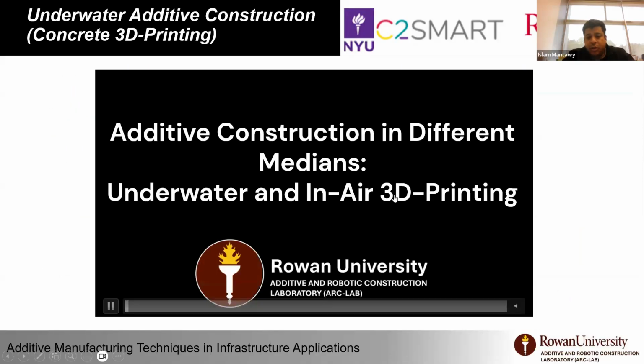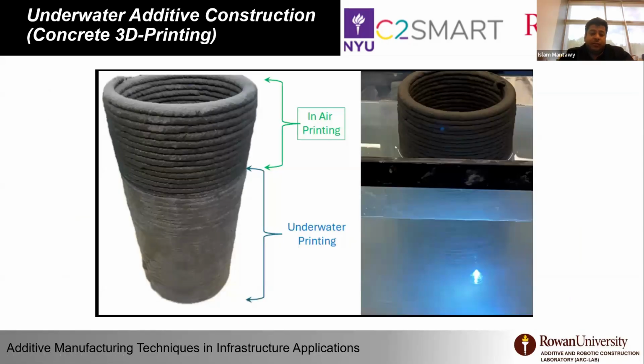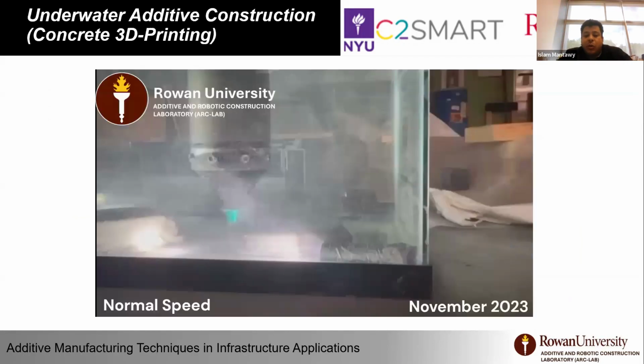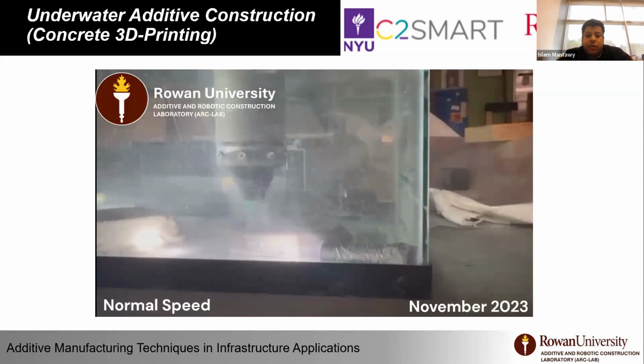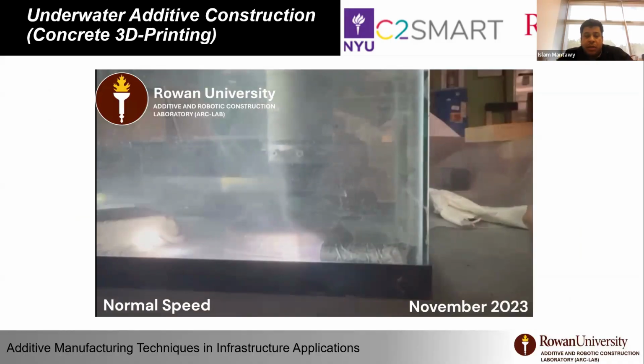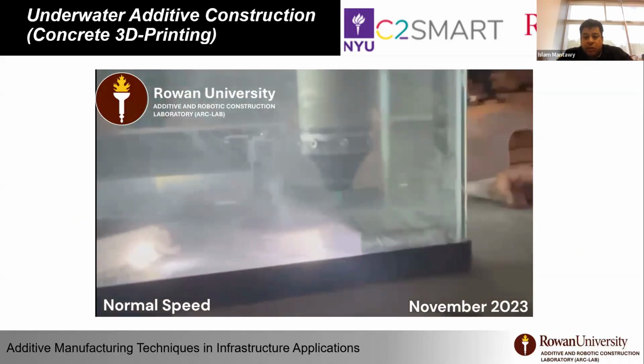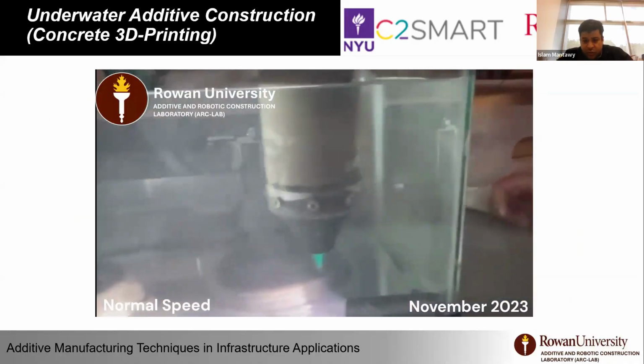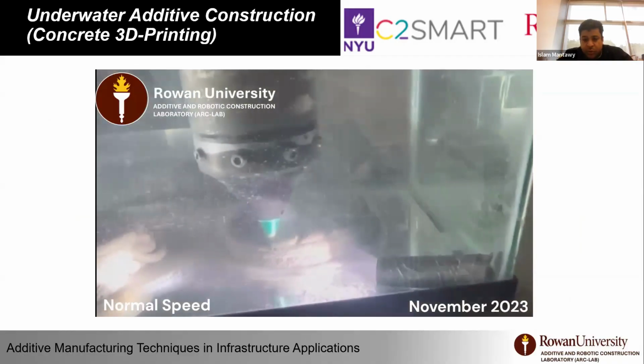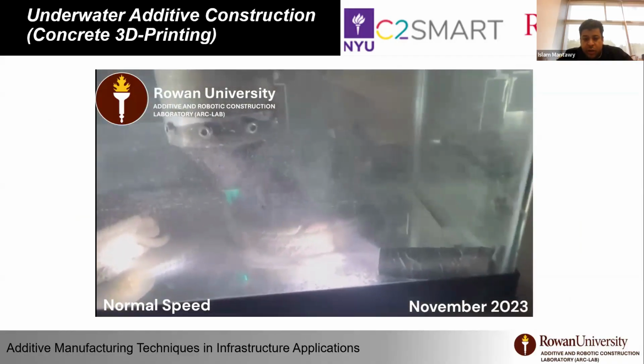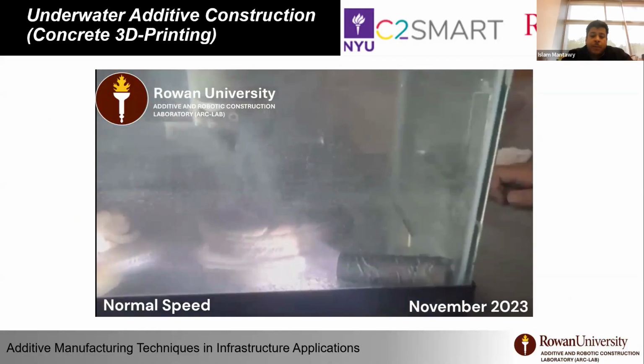In chronological order here from Rowan, we actually think we are one of the first people that printed underwater. That happened in November 2023, where we tried to see if we can print underwater, where water can be a medium for supporting slopes, to go to a severe slope as we print. So we print a structure underwater and off water.